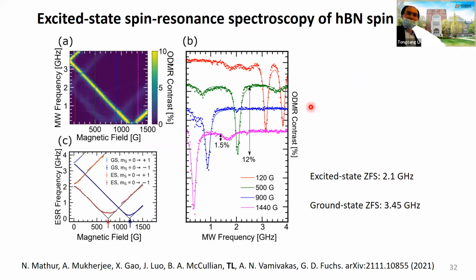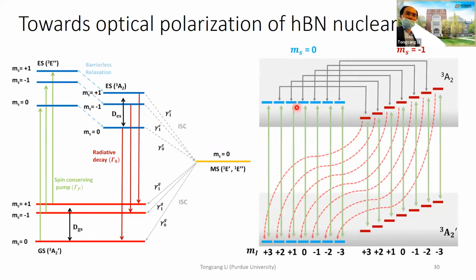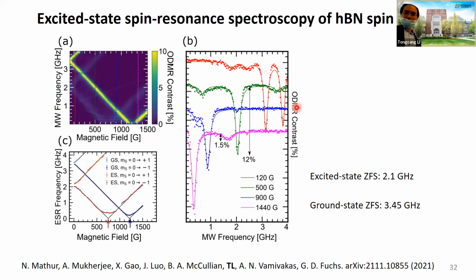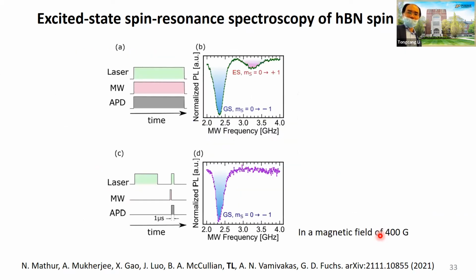Then we measured these spin energy levels as a function of magnetic field. You can see the excited state has a level anti-crossing at 750 Gauss, and the ground state has a level anti-crossing at 1,200 Gauss. So now we know the excited state zero field splitting is 2.1 gigahertz. In principle, we can go to these levels to perform nuclear spin polarization. We are working on that. These results have not even been published yet. Does this excited state zero field splitting match the modeling? Pretty close, not exactly, but pretty close.